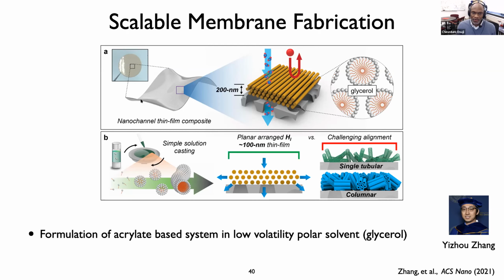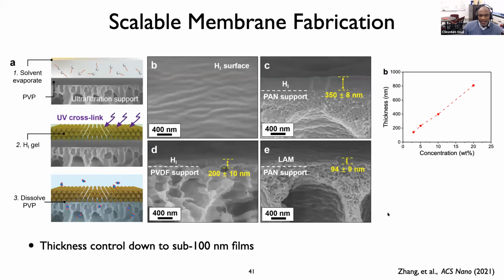And so all of the work, all of the magic was in finding materials with which we could formulate a mesophase using a non-volatile medium that would allow us to do solution processing. And so this was the work of a postdoc, Yizhou Zhang, in my group. And his results show that, okay, you can create now these thin films, selective layers that have thicknesses very similar to the selective layer thickness in reverse osmosis and commercial nanofiltration membranes, on the order of, say, 200 or 100 nanometers. And we can control the thickness of that selective layer very easily, simply by the concentration of the solution that we use to spin coat and fabricate these membranes.